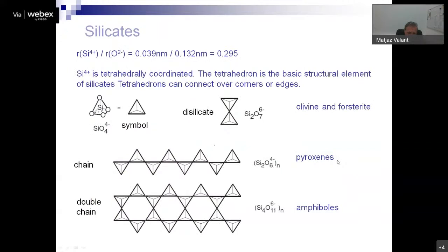There's this group which I would like to particularly mention, because it's very complex and very commonly found: all the minerals based on silicon, so-called silicates. The silicon 4+ ion is always tetrahedrally coordinated with oxygens because of this particular ratio between the ionic radii. For that reason, this tetrahedron is the basic structural element of the silicates. But these tetrahedra can connect in a variety of different ways. And depending on this, they form different families of the silicates. So they can connect over corners or over edges.